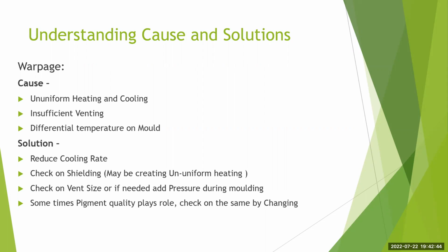So there it is required to do proper shielding also. Or sometimes you have to remove shielding to get normalized heating. Or you have to change the position of the mold, or change the arms also. So it's very important that you look at those aspects and see what the solution is. You have to see the vent size. The problem is that if there is low venting, there will be non-uniform heating or pressure created on the product inside the mold, which creates warpage or stress.